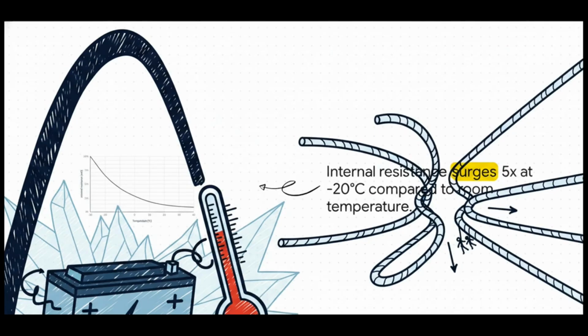The internal resistance at the electrodes, the solid electrolyte interface, and the electrolyte itself just skyrockets. Testing shows that at -20°C, internal resistance surges to 5 times its normal level compared to room temperature. It's literally like trying to force a massive amount of water through a tiny straw that's shrinking by the minute, which leads to huge I²R energy losses just from pushing that current through.